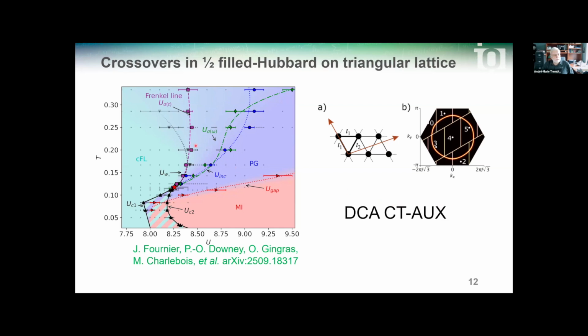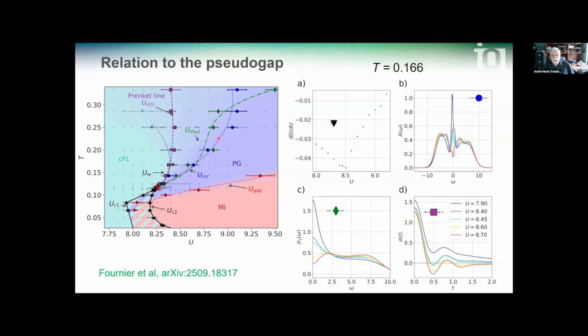The phase diagram is temperature versus interaction strength. By the way, we still need to work on the precise location of all these lines, so don't take them all too seriously, but their existence is established. At low temperature, there's the first-order Mott transition between metal at small U and insulator at large U that ends at a critical point. And there are a series of crossovers. Four crossover lines above the critical point are shown.